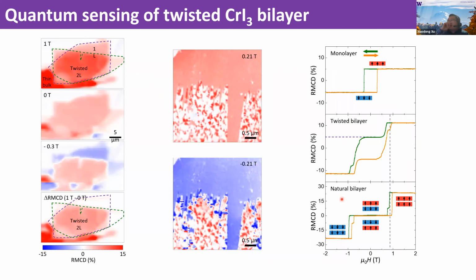Okay, so we can also perform the measurements at different magnetic fields and at different areas, for example. One thing you'll notice is when I change my magnetic field from 0.21 Tesla to minus 0.21 Tesla, which is larger than the coercive field of the monolayer, you'll see that the background monolayer signal already flips. But for the twisted bilayer, most of the pattern actually doesn't change.